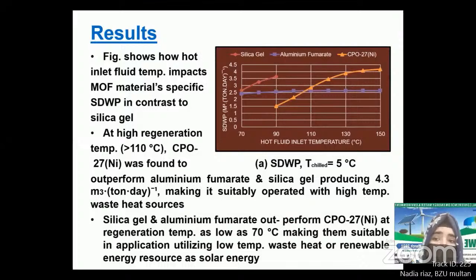The figure shows the effect of hot fluid inlet temperature on specific daily water production of MOF materials compared to silica gel. At high regeneration temperatures, higher than 110 degrees Celsius, the CPO-27 nickel was found to outperform the aluminum fumarate and silica gel, producing 4.3 cubic meters per ton in a day, which makes it suitable in applications operated with high temperature waste heat sources.